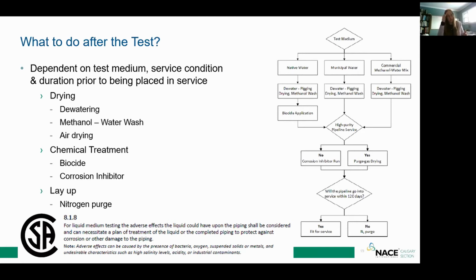There's a great paper back in 2018 called How Dry is Dry from Nova Gas, and they really explained how you can do dew point drying. It takes many hours. However, you get a great product in the end and is really your only option for those high purity pipelines. However, you have a chance to go with a corrosion inhibitor.